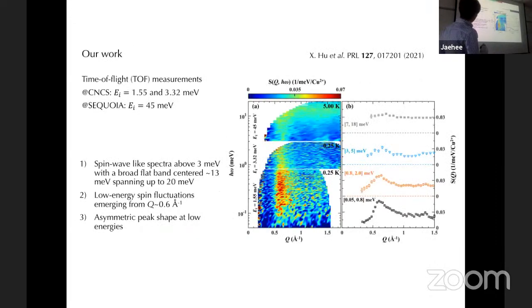So what we did was we chose very low energy. We set up the experiment so that we can probe extremely low energies. And we have to go down to very low temperature, so we use the dilution fridge. So this is the neutron scattering data. This is from 0.1 millielectronvolt all the way up to 20 millielectronvolt and so on. And you have this very nice dispersion, the spin-wave-like spectrum, well correlated.